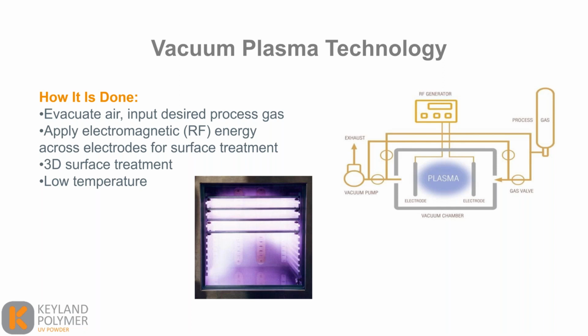So the way that this vacuum plasma technology works is the sample is placed in the chamber, the air is evacuated, the desired input gas is put in, and that can be either argon, oxygen, ambient air, or others. And then you generate and apply an electromagnetic energy across the electrodes, which ionizes the gas in the chamber and forms plasma. And if you're looking for some more detail into this than we're going to go over in the presentation, Scott Subreme has a very good article in the February 2019 edition of UV EB technology. So that's a good resource.